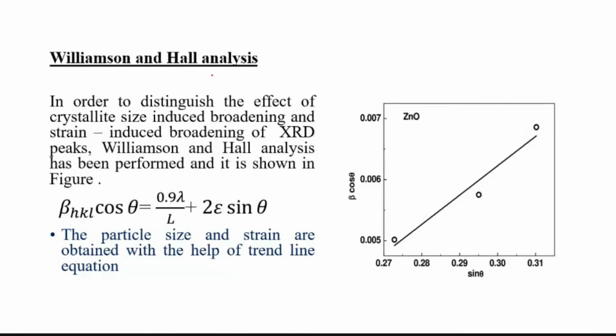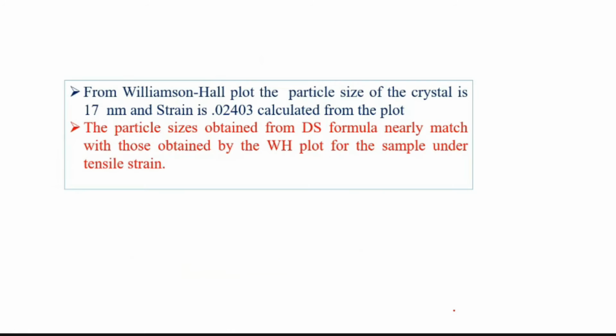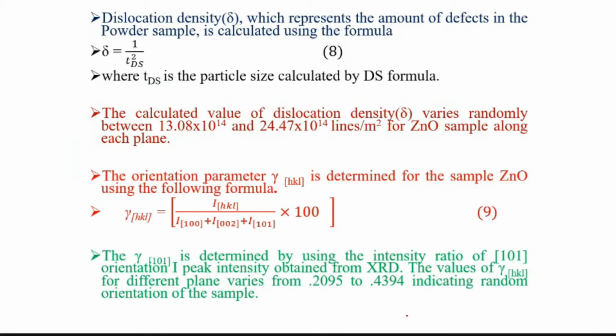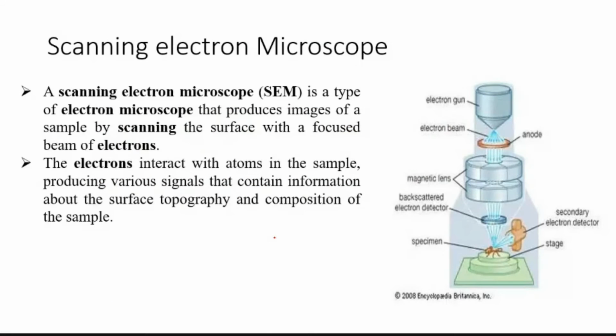We can also get the particle size by using the Williamson-Hall analysis. So this is the formula: beta cos theta is equal to 0.9 lambda upon L plus 2 epsilon sin theta. This is the Williamson-Hall analysis by which we can get the particle size of our material. We can also get the dislocation density, and we can also get the orientation parameter by using X-ray diffraction.